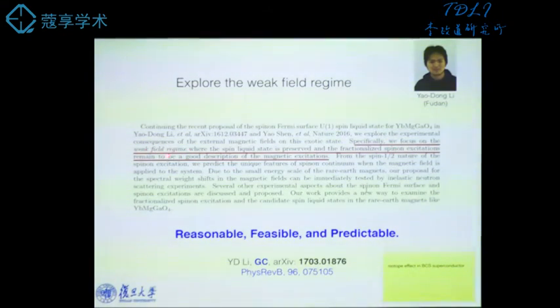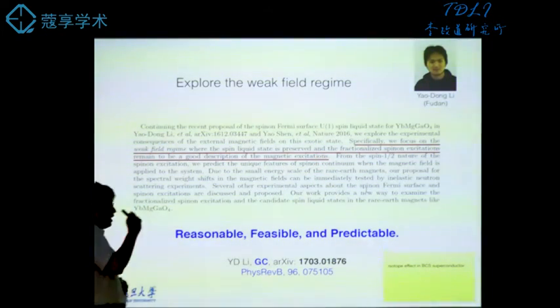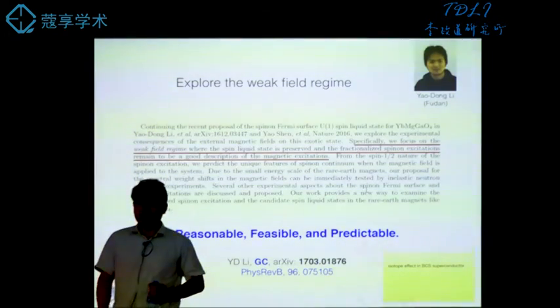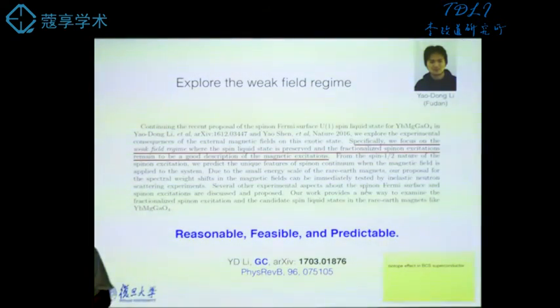We focused on the weak field regime, where the spin liquid is preserved and the fractionalized spinon remains to be a good description of the magnetic state. So we apply a weak magnetic field, weak such that the spin liquid state is not being destroyed. So you do something little to the system and look at the response. If this response can be theoretically predicted as a consequence of the fractionalization, and this prediction is confirmed by the experiment, that will give us a strong support that fractionalization does occur in the system.